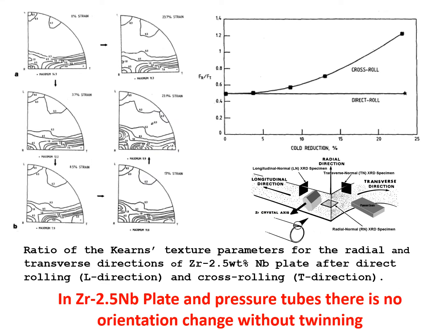So one way to give an example of why slip categorically does not change the orientation of the crystal is to illustrate this with some deformation of a plate where we can look at the texture changes. This is a kind of cruder engineering way of looking at this potential for orientation differences. So we have some zirconium plate, which has a very strong texture with the basal poles in the transverse direction.